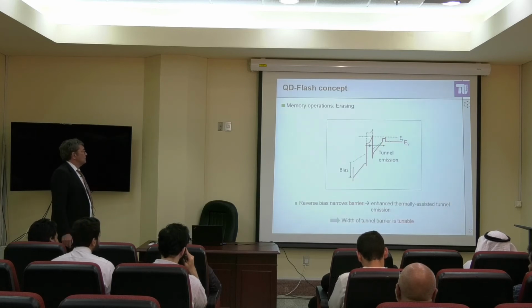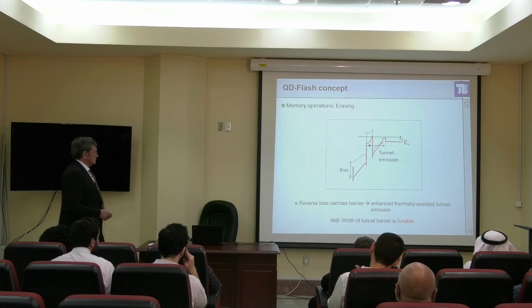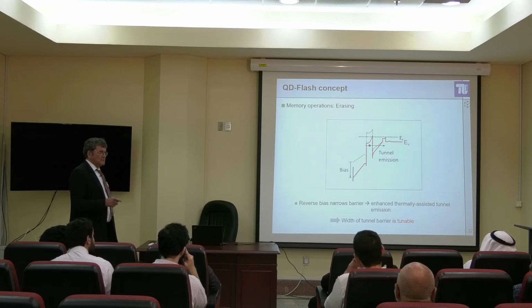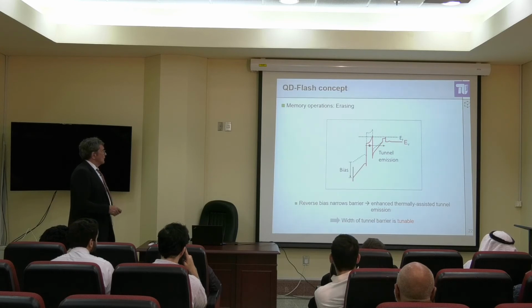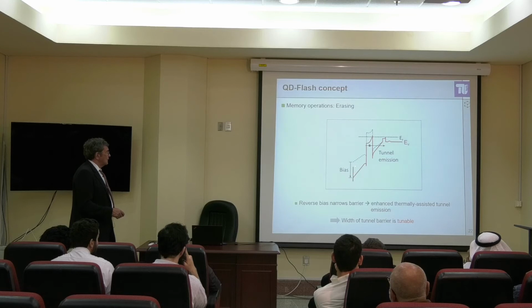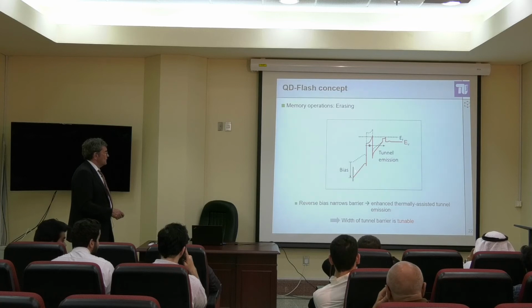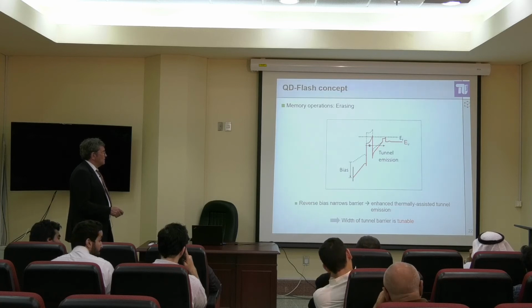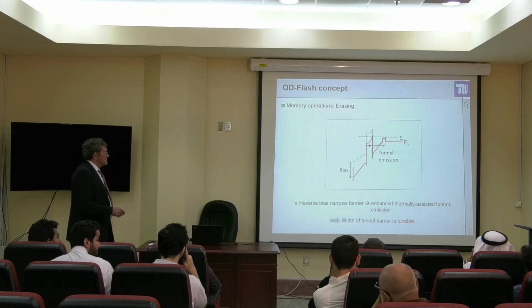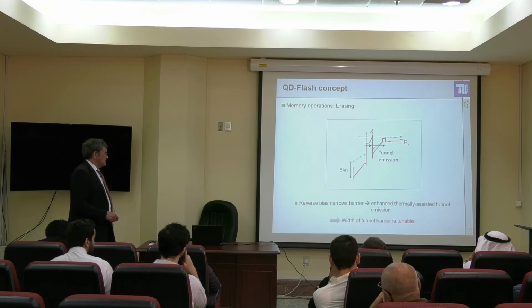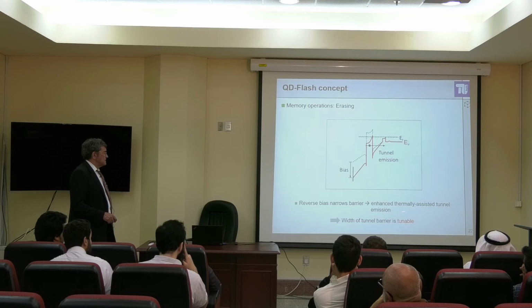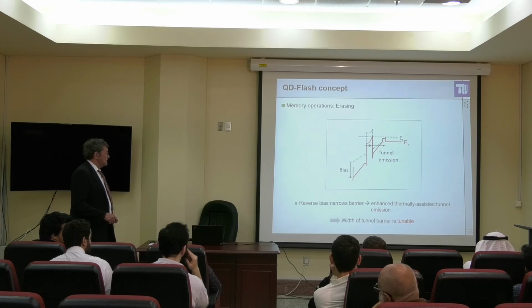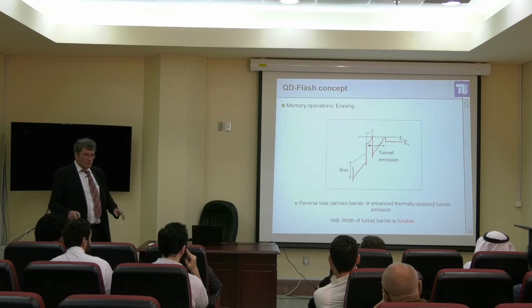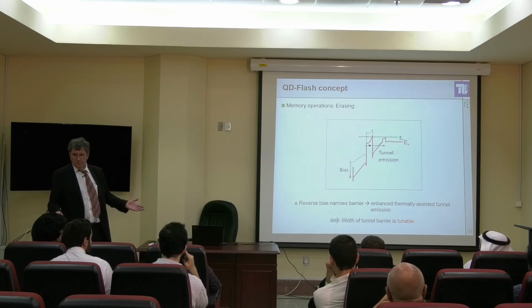So certainly no problem. Erasing. You do exactly the opposite of what I discussed before. You pull this energy level of the valence band down instead of up. And then you have a tunnel emission. You have a smaller width of the barrier, and you get it out. Reverse bias narrows the barrier, and you have an enhanced thermally assisted tunnel emission. And the width of the tunneling barrier is, of course, tunable by external voltage. Very straightforward, very simple.